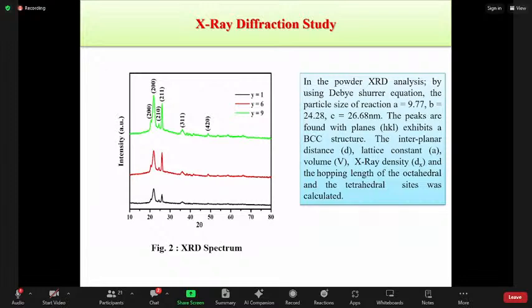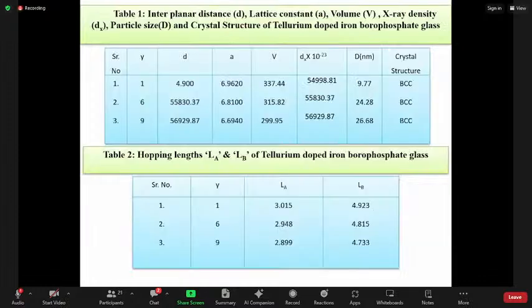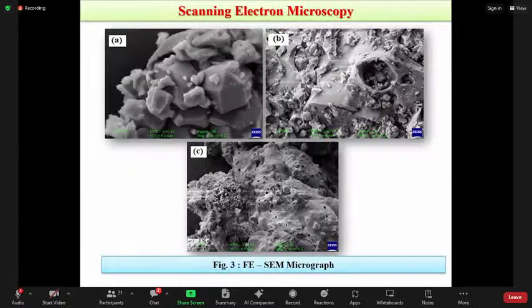With the help of the hkl planes, it shows a body-centered cubic crystal structure. Then the interplanar distance, lattice constant, volume, X-ray density, and hopping length of octahedral and tetrahedral sites are calculated as shown in the following table. Then we see the scanning electron microscopy.